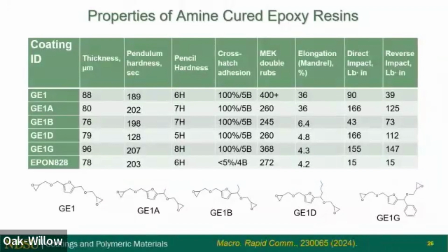And so one of the things we have done with these is made epoxy resins out of selected ones. Down at the bottom here is the familiar EPON 828. And we cured this with isophorone diamine just to do an initial study of these in coating formulations. And you can see we've got really hard coatings, very solvent resistant coatings, a little brittle, but all of these had much better adhesion than the bisphenol A epoxy. And so we think maybe that extra oxygen in there helps with adhesion to substrates. And so again, we're very interested in moving this technology forward and seeing if it can actually be commercialized.